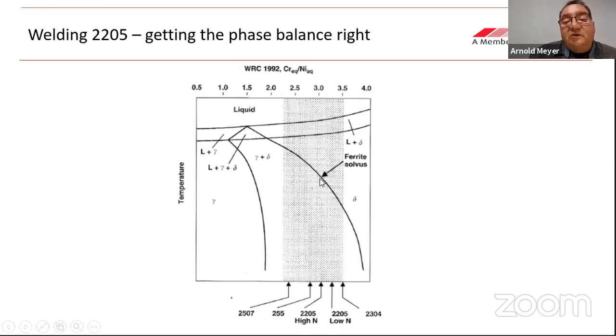Now, because welding is not equilibrium conditions, you actually have very fast cooling. If you go too fast through this region, you will not form enough austenite. In other words, that explains what I said before, that if you weld warmer, you will have slower cooling, more time to form austenite. And if you weld with a higher nickel content electrode like 2209, you will move towards the left-hand side here and have a larger austenite plus ferrite region, and that will give you more time to form austenite.